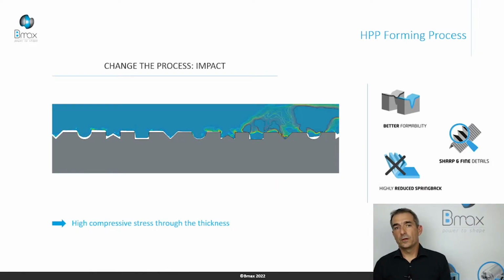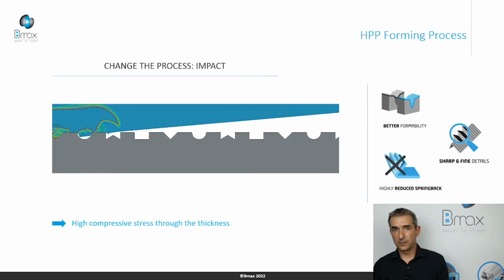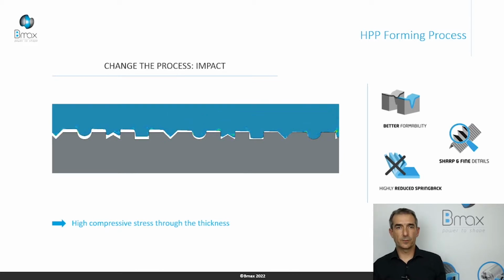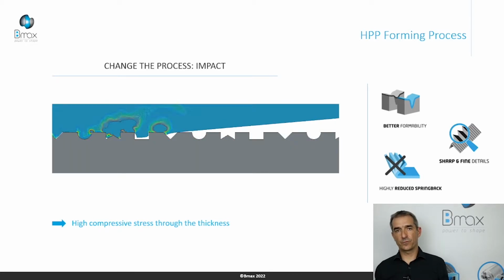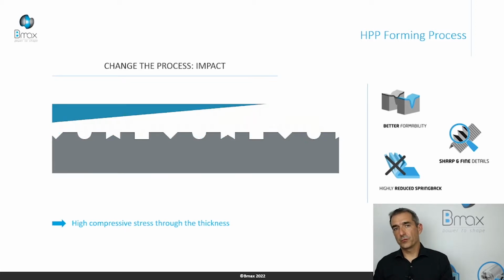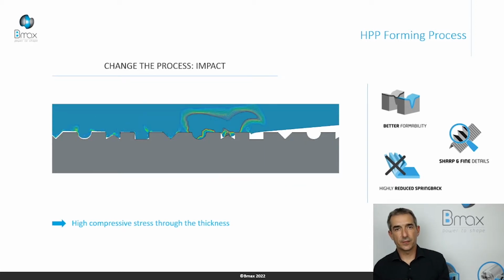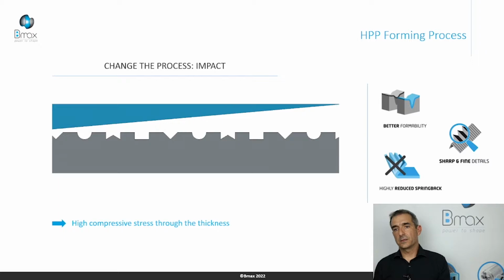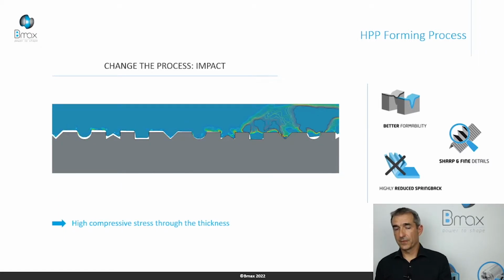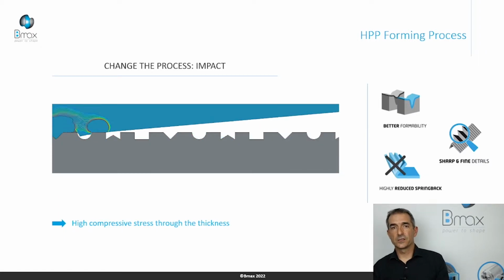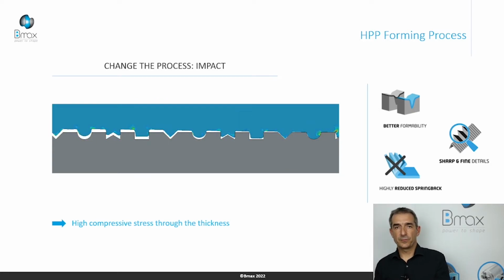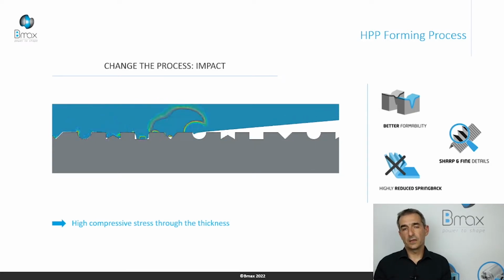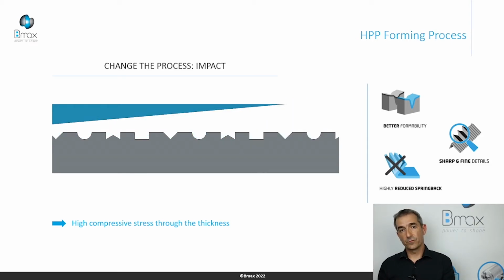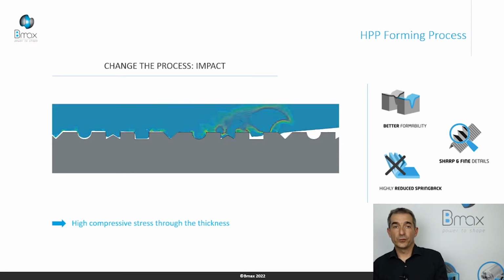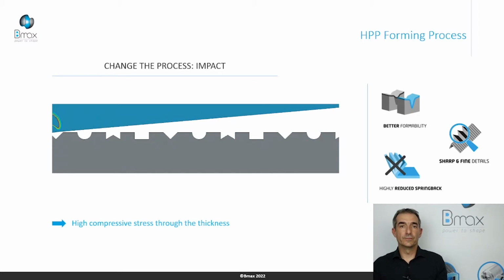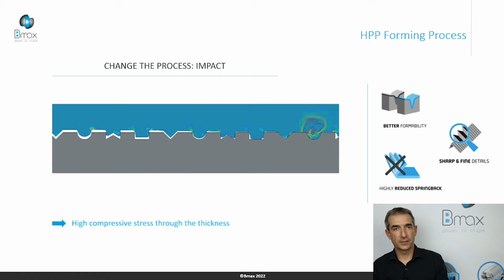With velocity at the impact, a few tenths of meters per second, for example, we can create megapascals of pressure. With the high pressure, we activate hydrodynamic behavior in the materials. The behavior of the material is like a fluid, even if thermodynamically it's a solid. In terms of pressure and temperature, it's a solid, but the behavior due to high pressure is fluid. In this way, we're able to engrave and to print any texturing on the blank.